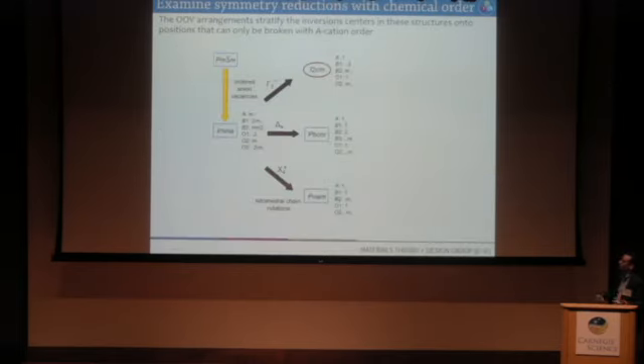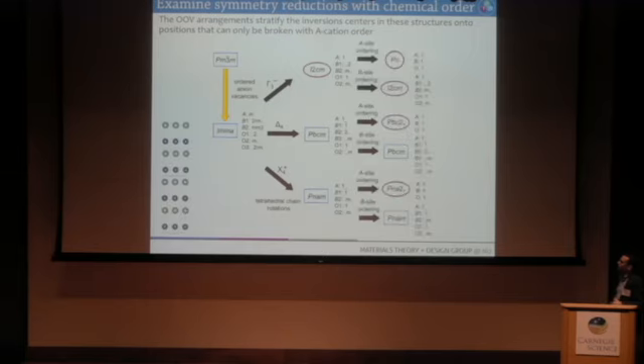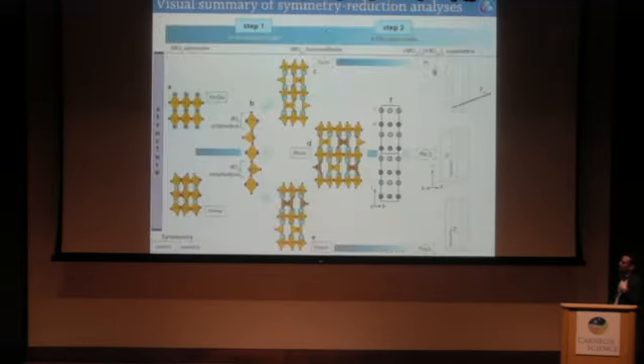And so you can go through the same exercise that I did for perovskite. Now this is for the brownmillerite phase. And you can apply chemical order either on the A site or the B site. You don't really need to study this. The only thing you need to notice is that the number of polar space groups, these ones circled in red, increase, okay, compared to the ones that maintain inversion symmetry. And so what we'll have is this tetrahedral, octahedral network and chemical order, and that will lift inversion symmetry.